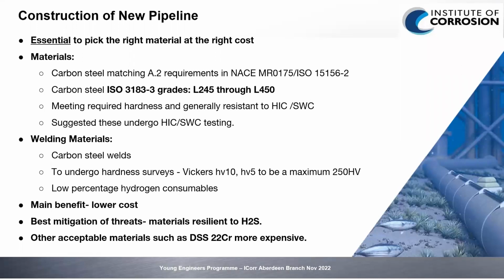Welding materials we would use, we recommend carbon steel welds, but these undergoing hardness surveys to understand if they're at the correct hardness levels and are more resilient to the risks. And we recommend low percentage hydrogen consumables are used to prevent introducing further hydrogen into the risk. So the main benefit of these materials is a lower cost, and they are mostly resilient to any of the threats coming in. There are other exceptional materials such as DSS 22CR, but with this being a more expensive price point, we believe carbon steel is the best choice for this.